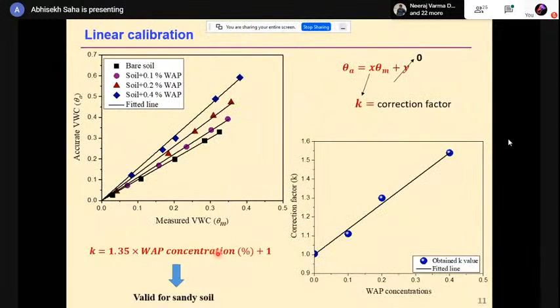So we have calibrated the values with the TOPP equation, and we have fitted the measured data points with a polynomial equation to obtain these parameters for calculating the volumetric water content. We have also used a linear calibration equation. In that, we are directly fitting the measured volumetric water content against the accurate volumetric water content. And we found that all of the lines pass through the origin, so the intercept value is 0. So the slope can be termed as a correction factor, which needs to be multiplied with the measured volumetric water content to get the accurate volumetric water content.